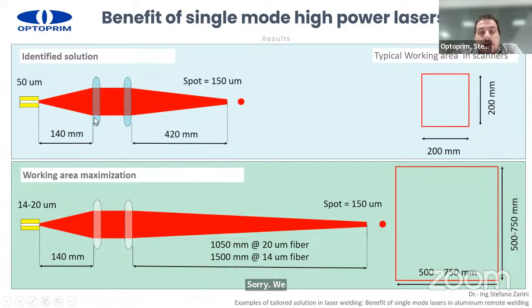We can keep the same collimation length, but we can enlarge the focusing distance up to 1050 millimeters or 1500 millimeters according to the fiber size, achieving the same spot size. In this way, we can clearly maximize the working area, and thus we can avoid using a robotic arm and so on, and we can work directly with a fixed scanner.